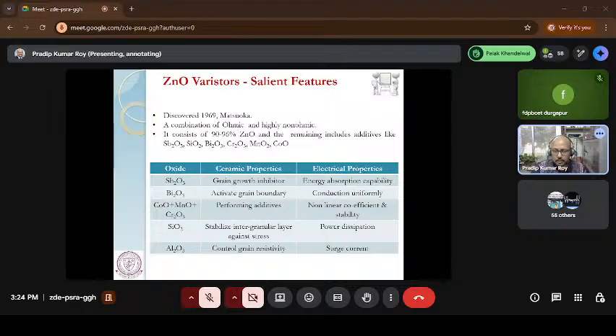All transition oxides like cobalt, manganese, chromium increase the non-linear performance of the surge arrestor. Non-linear means that for a small change in voltage, a huge amount of current will pass through the surge arrestor. And the rest of these two, silicon and alumina, are a little bit responsible for the losses parameter, which is very essential, normally what we call the watt loss. These two oxides are very much responsible for that. So this is basically a multi-oxide system used to manufacture the varistor.